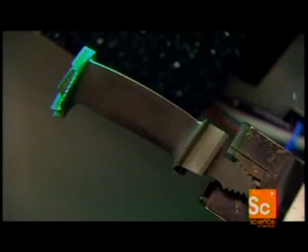To allow each turbine blade to self-cool while the turbine is running, tiny holes as small as 310 microns in diameter are made along the length of the blade. To make such small holes, they use hollow brass electrodes and a current of water to cut into the nickel alloy. When the engine runs, cool air will be passed through these perforations to prevent the blade from melting. These improvements in blade cooling technology have helped make more efficient, high-temperature engines possible.